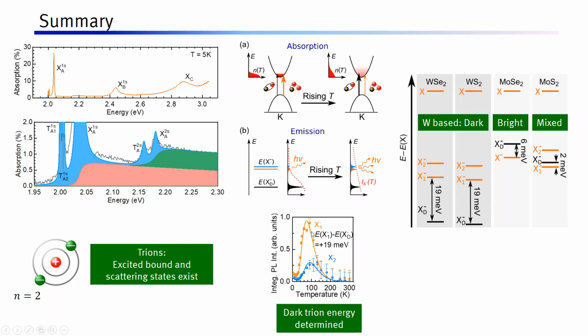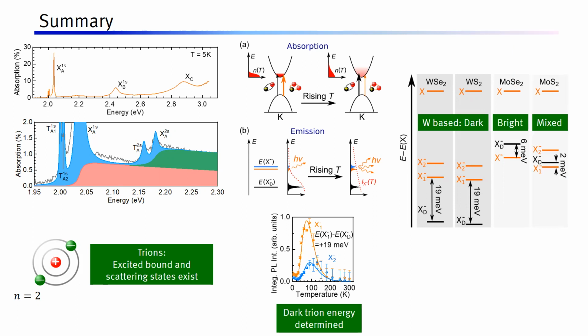Actually, this is experimental error. The thing is the following. This curve is obtained by measuring absolute intensities in the experiment, and you can have lots of problems doing that. First, you have to maintain the same laser excitation intensity, then you obtain a spectrum and take the area under the curve, which has some inherent error. The other problem is the spot on which you are exciting the sample. It has to be absolutely the same. If the spot moves a little bit, the intensity changes. So this is actually a luminescence intensity.